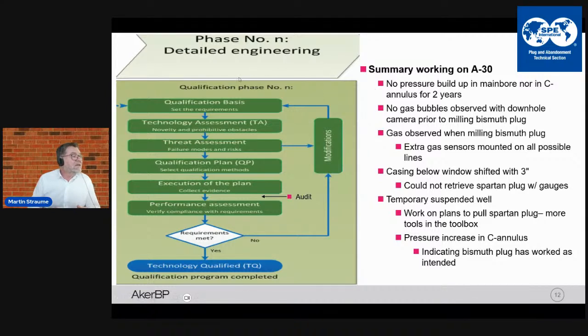Again, we went through this qualification process, and we met the requirements, what we think we did. So 2 years, that was good proof in the pudding. And like Marcelo mentioned, bismuth material is impermeable, and we have done tests beforehand with other universities that actually showed that it was corrosive resistant as well. And it resisted CO2 and it resisted H2S.